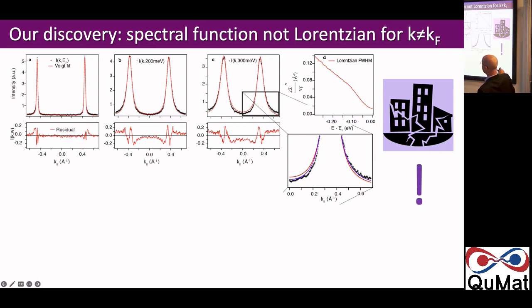And if you then go to 200 millivolts below the Fermi level, so this is some k vector, I don't know what it's going to be, 0.1 reciprocal angstroms below kF, you start to say, it's okay, but the fit is always giving us a bit too much intensity in between the two peaks and a little bit too little on the outside. We go to 300 millivolts, it's getting even more. So you can still get these power law liquid exponents from this kind of fit, but we're not happy. We're missing something in the data.